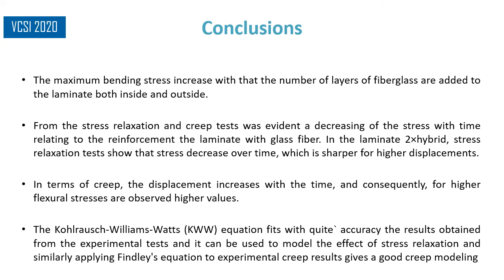Conclusions. The maximum bending stress increases as the number of layers of fiberglass added to the laminate, both inside and outside. From the stress relaxation and creep tests, a decrease of the stress with time is evident in relation to the reinforcement of the laminate with glass fiber. In the 2×hybrid laminate, stress relaxation tests show that stress decreases over time, which is sharper for each displacement. In terms of creep, the displacement increases with time, and consequently higher flexural stresses are observed.